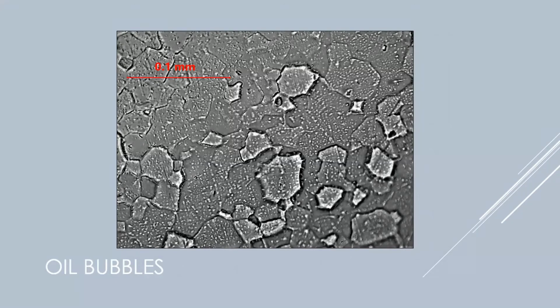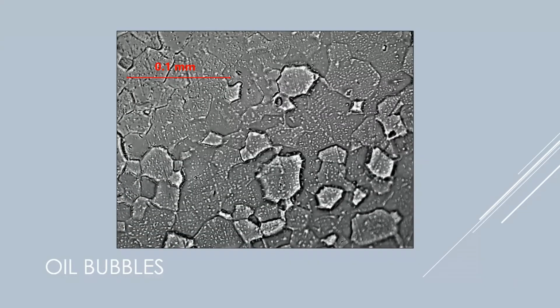I put this one in here because if you look at this one, this has got all sorts of little spots over it too, eh? And you go back to this one, so does this. But these spots here and this one, it's different. This is an artifact. And you have to be able to just look at that and just say, okay, I mucked up there. What happens is the diamond paste I polish with is oil-based. And the only way you're going to get that off the surface that you're grinding and polishing is you have to use dish soap. You can't use hand soap or anything like that. Dish soap will take off the oil. If you try ethanol or methanol or some sort of solvent, all that oil does is form little balls of oil on your surface, and it gets onto your replica. So it looks like this thing is covered with iron carbides when really it's just drops of oil.